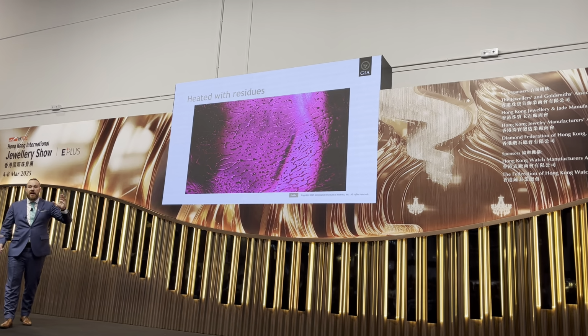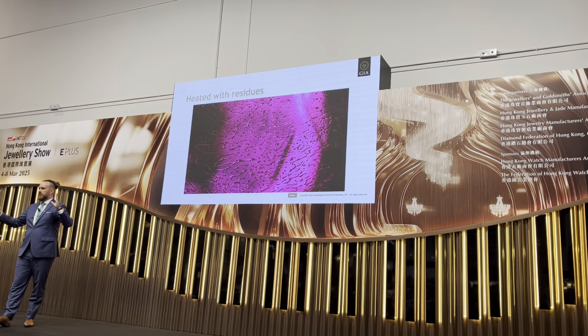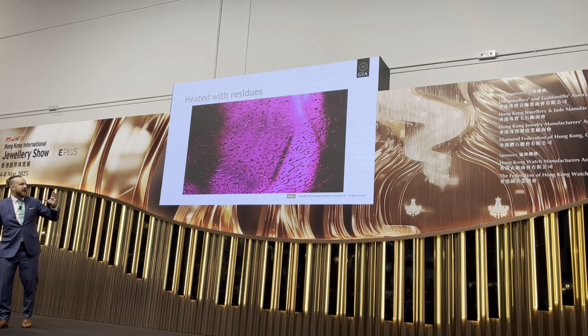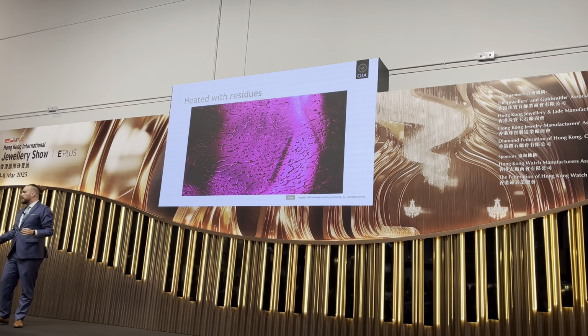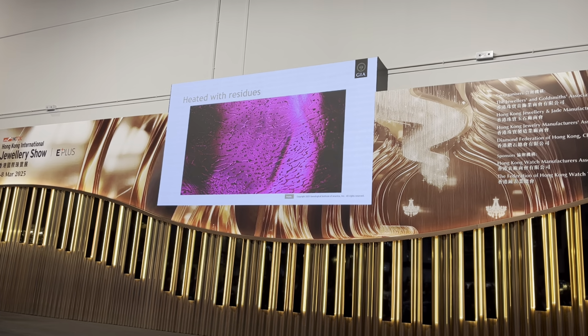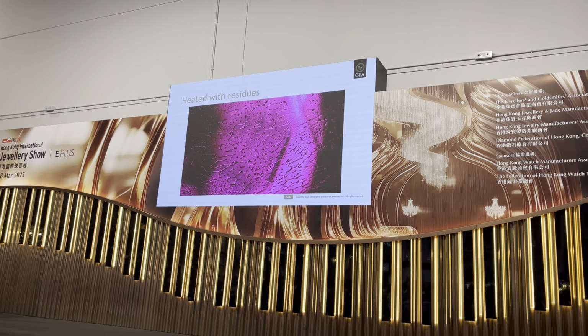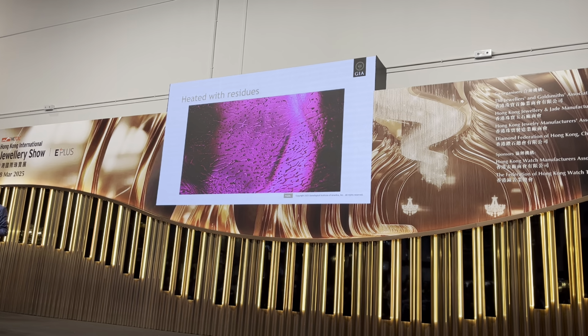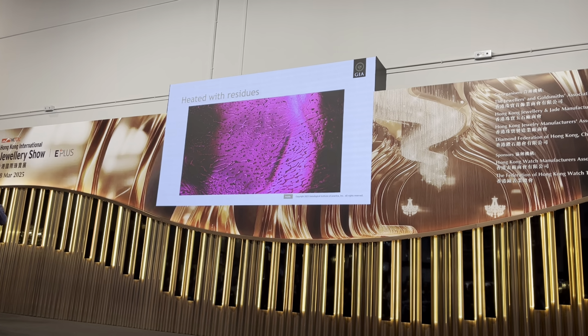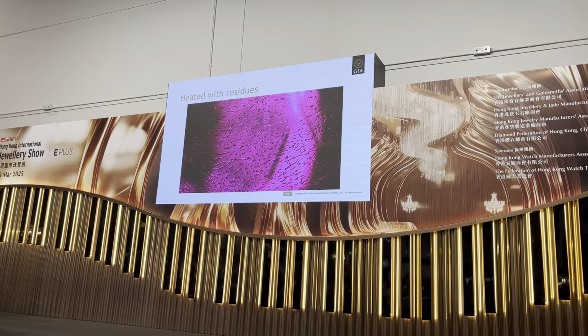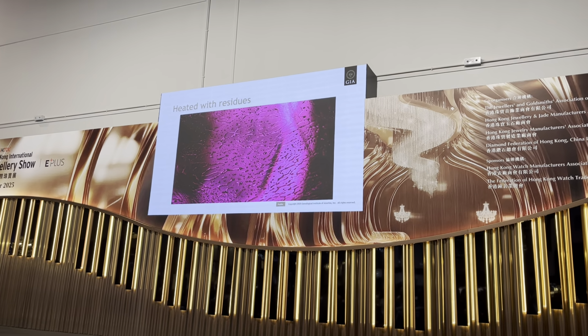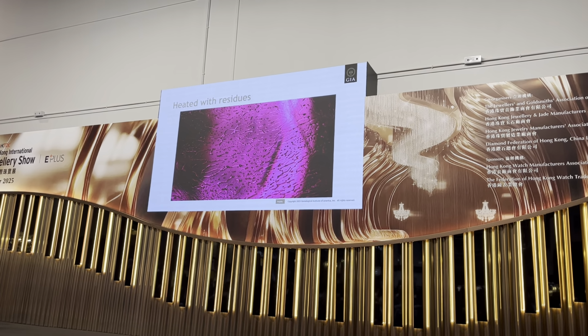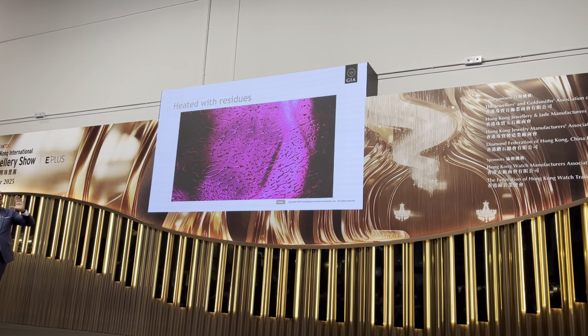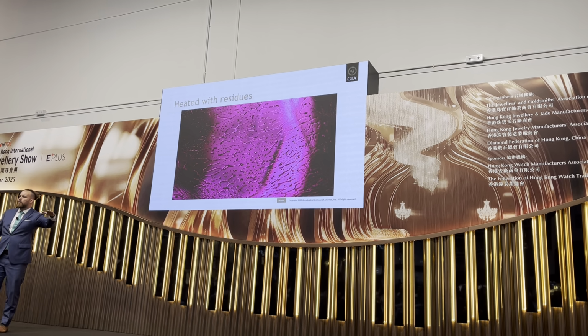And this is what is left. So this used to be a completely open fracture. This used to be filled with air. But now you can see that there is only these droplets of flux that remain, that is the scar, but most of it is actually filled with corundum now. So it has the same hardness, it has the same durability, it has the same chemical resistance as the rest of the corundum.